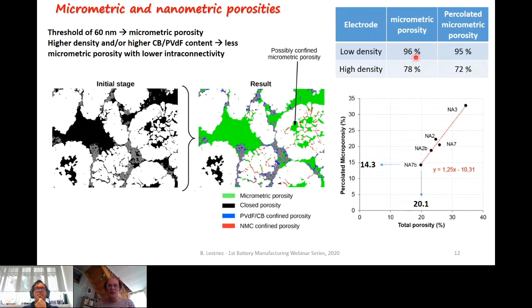So if you do the quantification, you see that the micrometric porosity is the main part of the total porosity. But if you look at the denser electrode, you see that, for example, among the 5 volumes we have studied, the denser one, the micrometric porosity is only 78% of the total porosity. And then if you remove these ones that are inside clusters and are not directly in contact with the rest of the micropores through micropores, there is a kind of interface here. The junction here is only through nanopores. We have removed this part to quantify what we call the percolated micrometric porosity, which is lower than the micrometric porosity. And you see that for the denser electrode, the percolated micrometric porosity is only 72% of the total porosity.